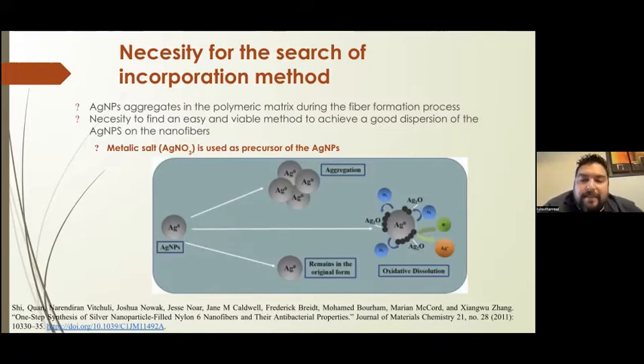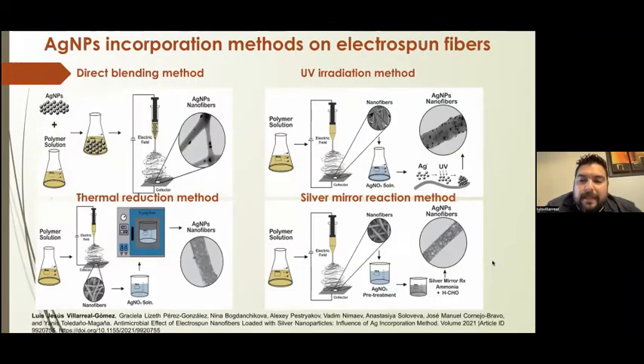So in my part, we have the idea to load these silver nanoparticles into the fibers, but we found that there are several strategies to do so. Mainly, we found 4 different methods, and we searched the literature and found a lot of work on these 4 methods, but they do not report the same conditions, or they do not characterize with the same techniques. That's the necessity to compare these 4 methods under the same conditions, and to see which one of these methods is the best.